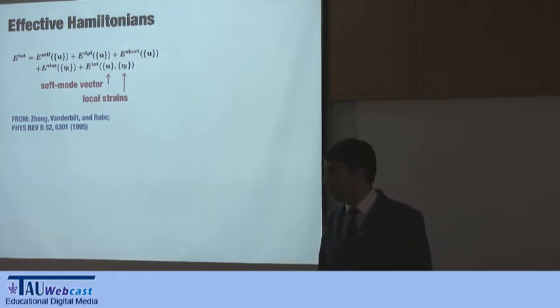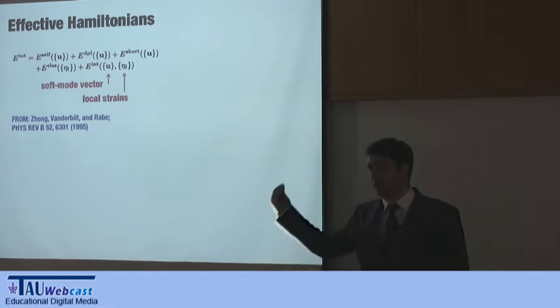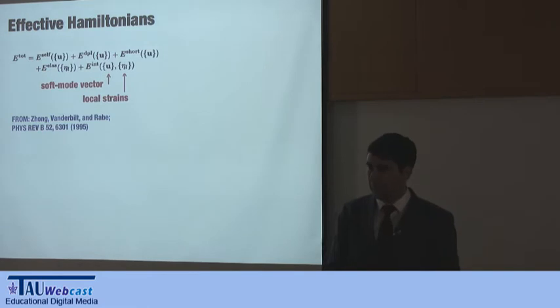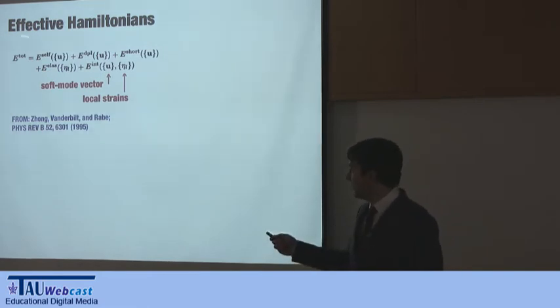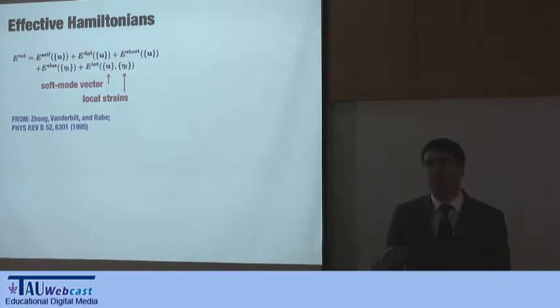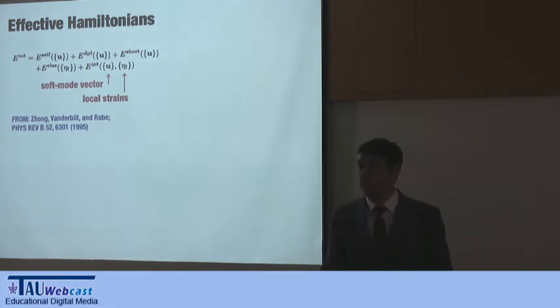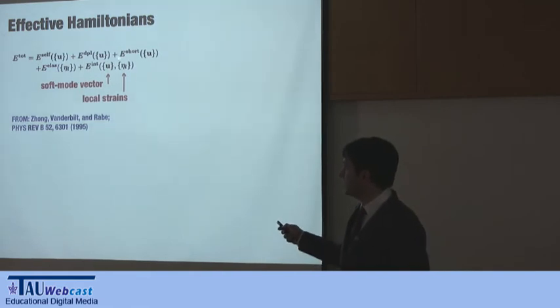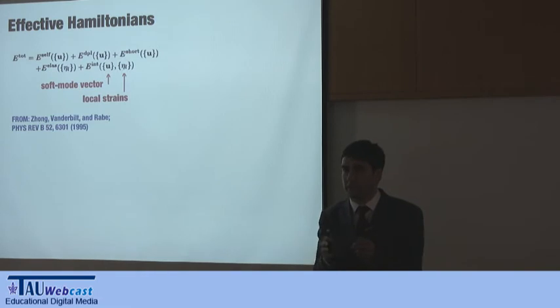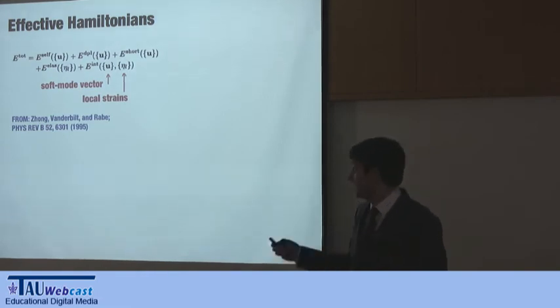An approach you can take is an effective Hamiltonian or effective potential, in which you go to your material, you pick which variables are important, and then you come up with an energy as a function of these variables. And this is what they did, for example, in the group of Vanderbilt in '95. The energy is expanded as a function of the local strains, so for every cell, how much it contracts or expands, and the soft mode vector.